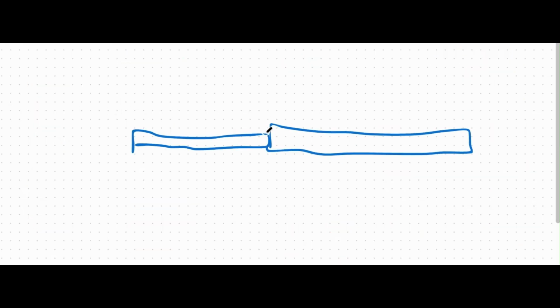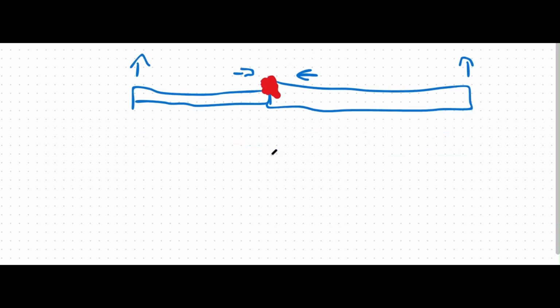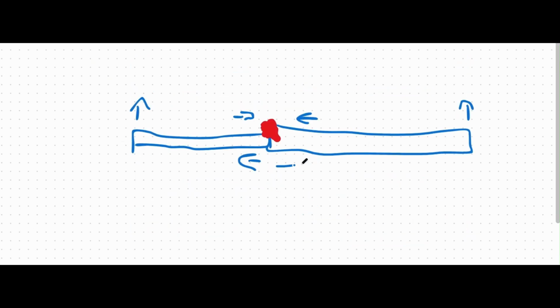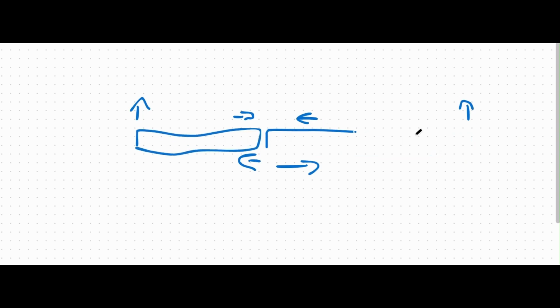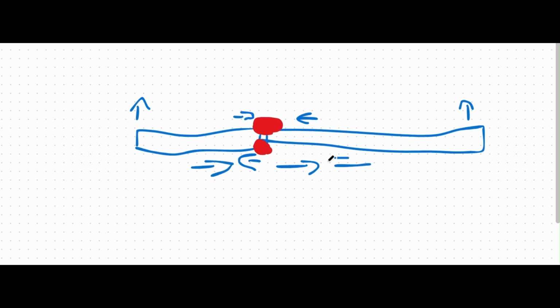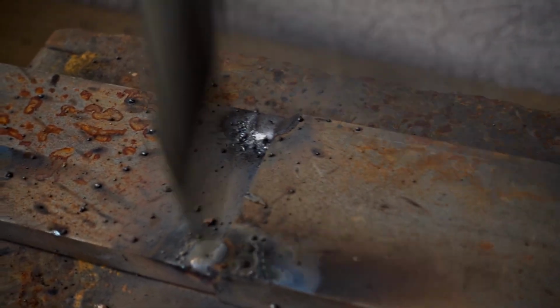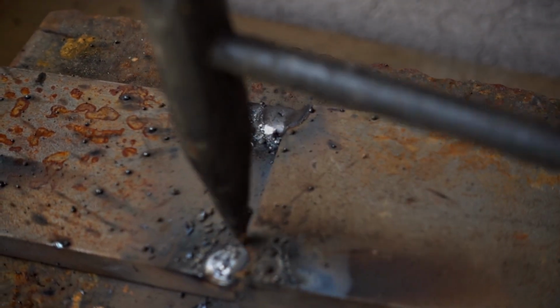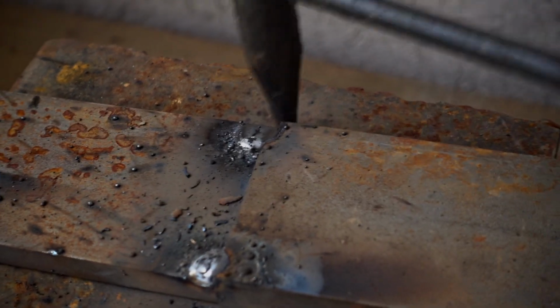Weld two pieces together without tacking them first. What usually happens is that by the time we finish the weld, the high heat causes the metal to contract. This often makes the ends of the pieces lift up slightly, forming a kind of bow or belly shape, which is definitely not what we want. To avoid this, it's common practice to add a few tack welds on the opposite side of where we're going to run our main bead. These tacks help hold everything in place and stop the metal from warping or pulling apart due to heat. So, by adding some tack welds before starting the full weld, we can keep the pieces aligned and avoid distortion caused by temperature changes.